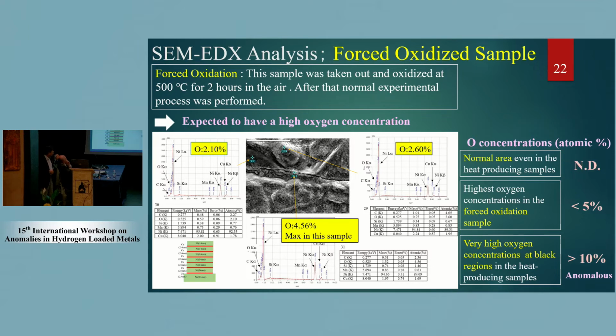So normal area, even in the heat-producing sample, non-detection of oxygen concentration. And the highest oxygen concentration in the forced oxidation sample, less than 5%. Even though forced oxidized, less than 5%. But very high oxygen concentration at the black region in the heat-producing samples, larger than 10%. I would like to say it is an anomalous result.